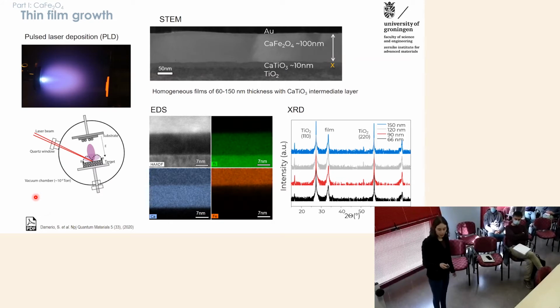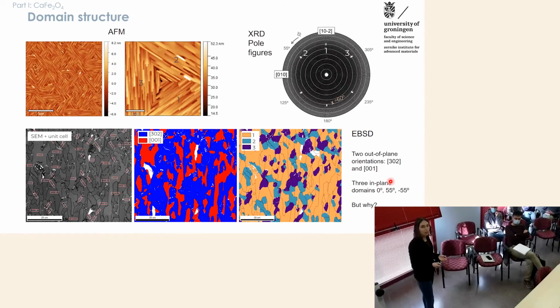So after this, we characterize our films by means of XRD. So this is a normal out-of-plane theta-omega scan, and you can see a clear film peak appearing at about 33.5 degrees. Interestingly, in the crystal structure of this material, this peak could be attributed to two different crystallographic orientations. So from these measurements only, we couldn't exactly tell what was the out of plane of our film, either 001 or 302. So we perform more measurements, but before that, we also just look at the surface of our samples by means of AFM.